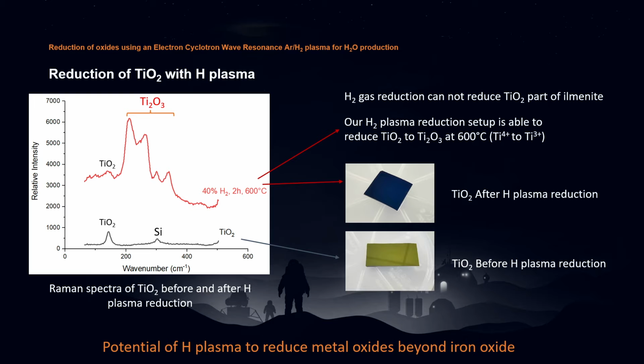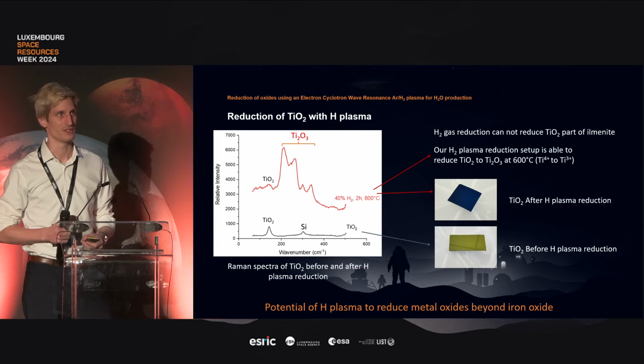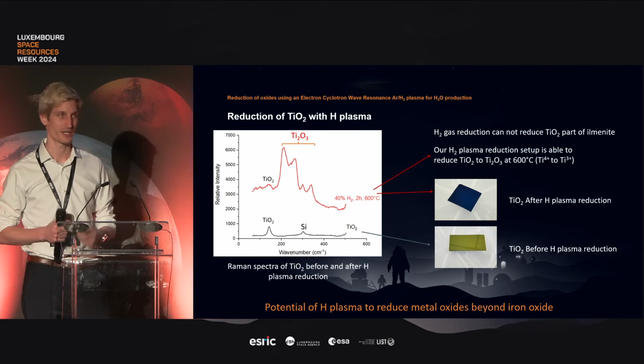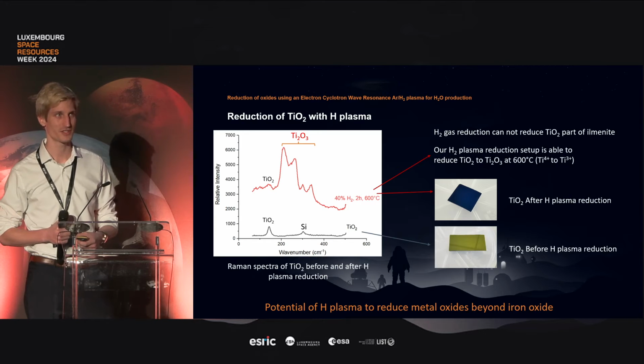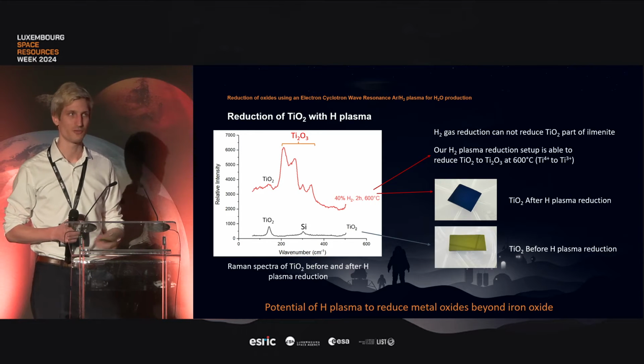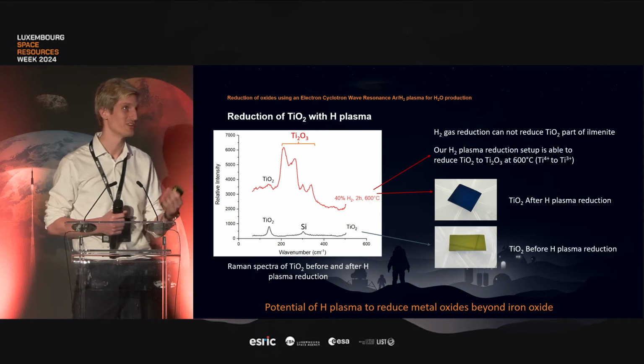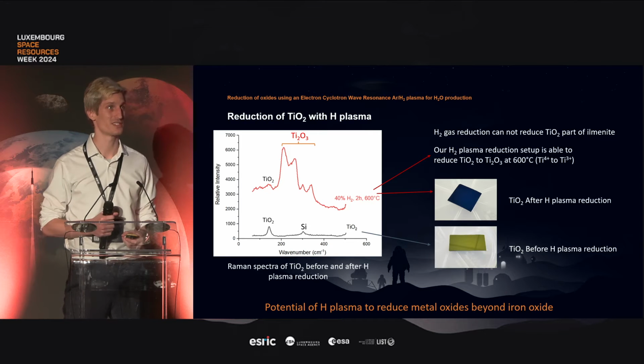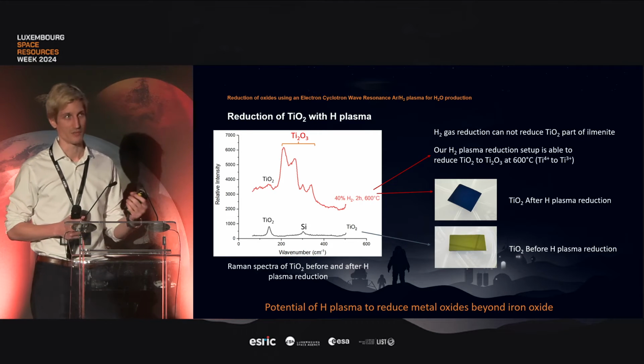Lastly, we also wanted to preliminarily test, can we go beyond the iron oxide with hydrogen plasma with our setup, because this is one of the limitations of the hydrogen gas reduction process. And we performed some preliminary investigation with that and reduced it at 600 degrees.